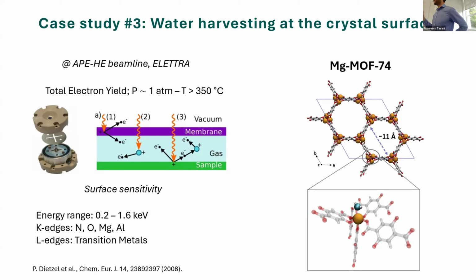We actually applied this technique to investigate the properties of magnesium MOF-74. This is another prototypical MOF in the MOF literature. It is constructed with these hexagonal channels, approximately 11 angstrom wide. And the magnesium sites directly coordinate water molecules.